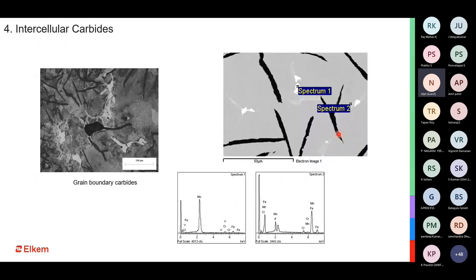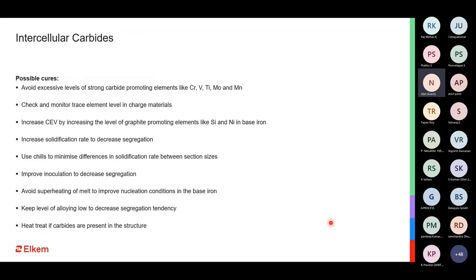Carbides, again, are one of the major problems, something which causes a lot of machinability, shrinkage, and mechanical property issues inside the casting. Grain boundary carbides are caused mostly because of the presence of carbide promoting elements, very fast solidification of the casting, insufficient inoculation, etc. What we are trying to show here is, if you look at this microstructure using a SEM, you can see some amount of free carbides present, and when we did a chemical analysis of those, we were able to find a high percentage of molybdenum, chromium, vanadium, etc. So these are, like we have always said, the actual carbide promoting elements, and wherever you see carbides, they are actually coming from these elements.